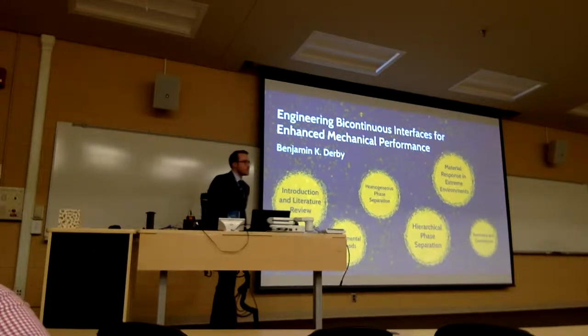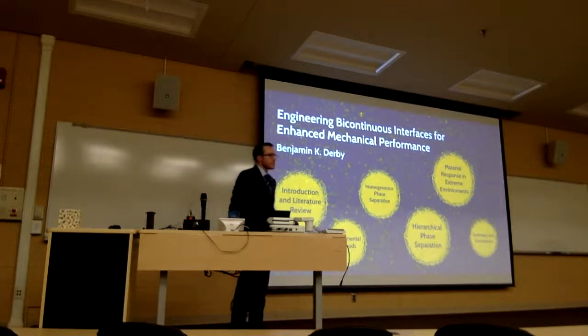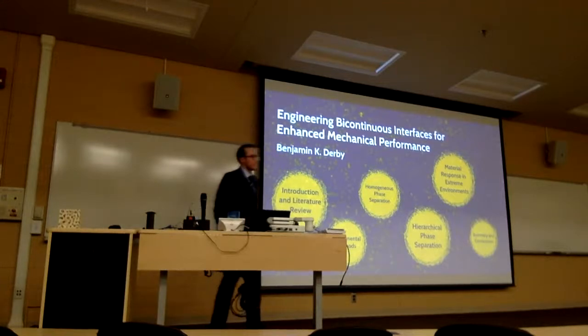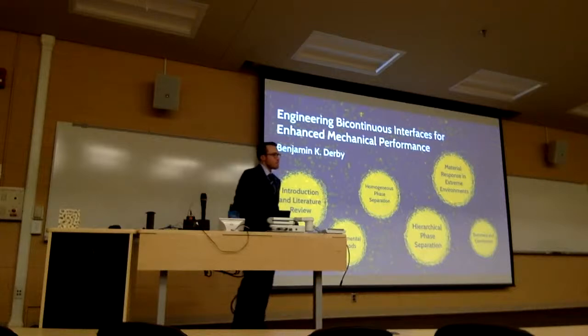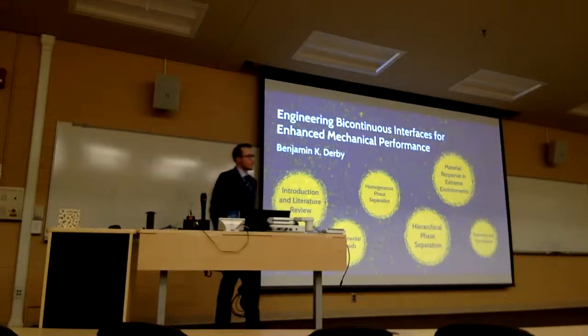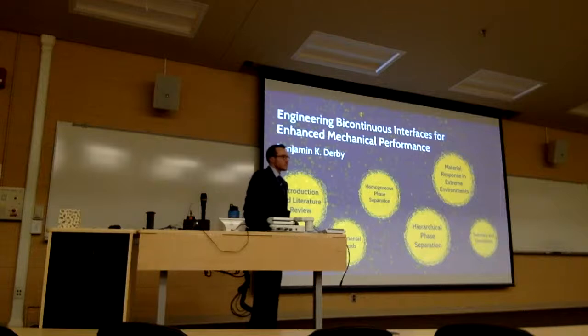Another thing then, given that you probably need to take in the diffusion coefficients for both components that are pretty different to model those dynamics in the heterogeneous system as well, did you ever vary the deposition rate of those two things to get at that? Do you really have control over those deposition rates individually? You actually jumped the gun. We're trying to do that right now, to see if we can change the diffusivity of those constituents based on the deposition rate. Here I just showed you results for two different deposition rates. We're limited to a range of deposition rates, but yes, we can play with that aspect of the deposition to vary those parameters.